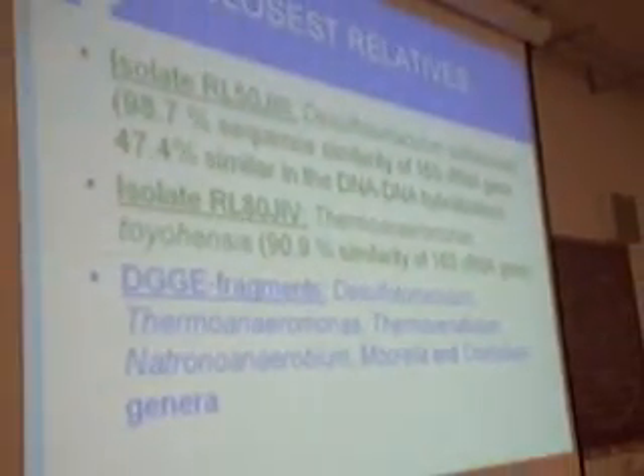And the other isolate, which was isolated at 80 degrees, was most closely related to Thermoanaerobacter toyohensis, about 90.9% similarity, so it is possibly a new genus. And here are the closest relatives for the DGGE fragments. So then we decided to characterize the isolates more because they seem to be novel species or genera.